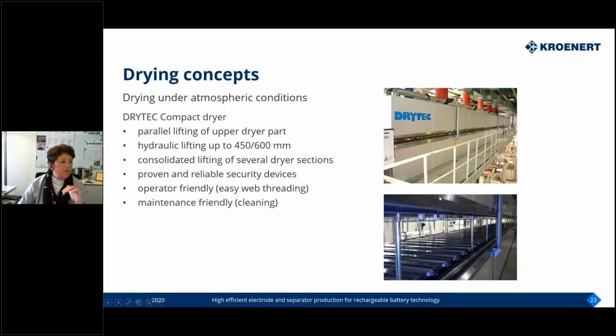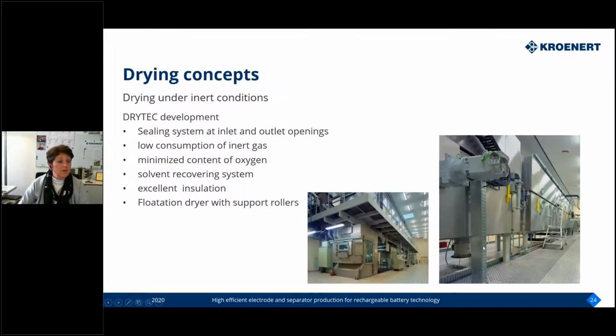As soon as we go to a wider working width, we have a completely lifting system so that the dryer is opened in a completely parallel lifting, and then it's quite easy to reach all the nozzles for cleaning or maintenance or whatever is necessary to handle the dryer. With the dryer, we can operate for sure in an explosion-proof range under standard atmosphere, so no special atmosphere in the dryer, but we also can handle such a dryer in inert atmosphere. It's quite often used to minimize the oxygen content in case a solvent recovery system has to be installed. In that case, you have already the oxygen out.